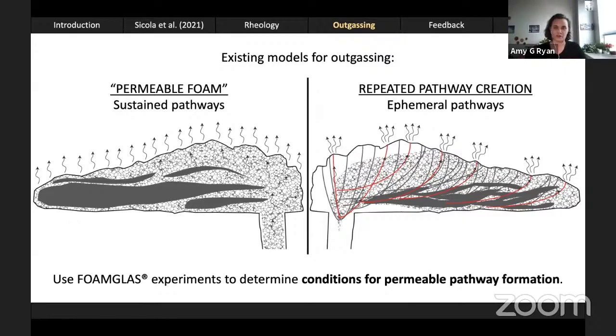The other conceptual model for physical outgassing is really a compilation of a bunch of more recent studies, which propose that thin permeable pathways are created either as a result of very localized bubble coalescence or melt fracturing. These ephemeral pathways allow for bursts of outgassing. But once the volatile phase has been lost, there's nothing to keep them open any longer. They close in on themselves and seal, and that outgassing pathway is lost. So for this model to work and for outgassing to be efficient and give us thick bands of obsidian in these lava flows, permeable pathways would need to be continuously created.